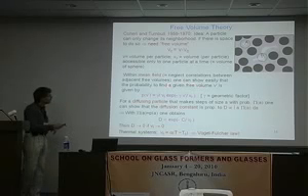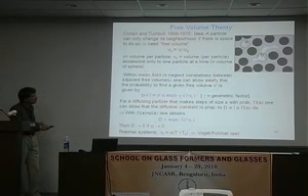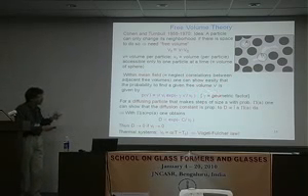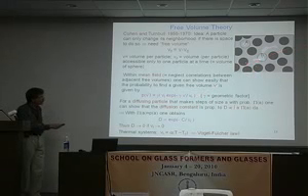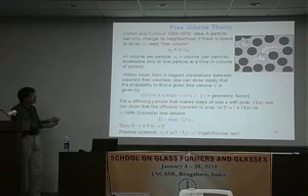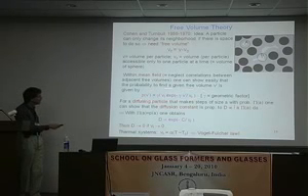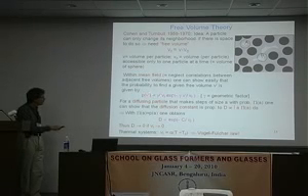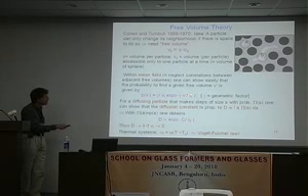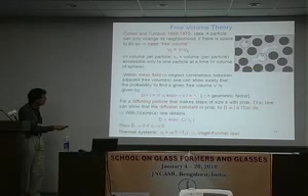And now you can make a very simple calculation. It's really not difficult. And then you find that the probability to find a free volume of a certain size is given by this expression here. The probability to have a free volume of size V' is given by a prefactor times exponential of minus a prefactor times V', with V_F in the denominator.